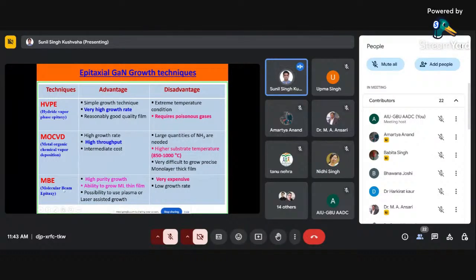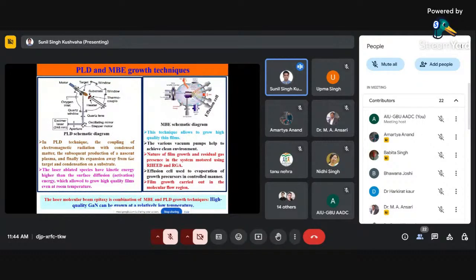That's molecular beam epitaxy. If you want a high growth rate, then of course you can use HVPE. Here you don't have the control, but if you want a thicker film, like 400, 500 micrometers, then you use HVPE, because MBE will take maybe 2 days to grow 400, 500 micrometers. So that's the reason it depends on what the application is. Then accordingly people select the techniques, and then again select the substrates, because the substrate is also important. Whether you want sapphire or silicon carbide depends on the application. I will not go into more details here.